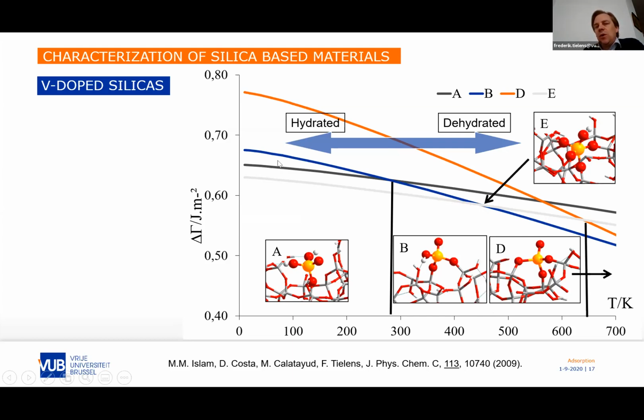In the way the experiments were performed, we did not have this type of structures. So we went to the grafted structures, with 1, 2, and 3 linkages, and then we could also define the stability domains on the temperature axis.